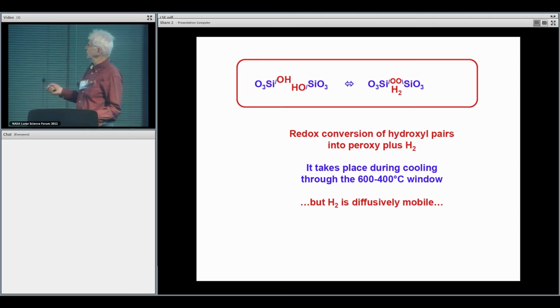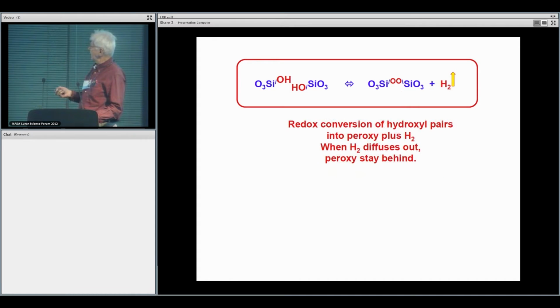This peroxy bond is a very short bond. It's only 1.5 angstrom long. The volume, if you draw a box around it, is barely that of one oxygen. Now, the next slide shows that hydrogen is diffusively mobile and could leave the place where this reaction has taken place, particularly if it has lots of time and additional activation. And if this happens, you would reach a situation which is quite interesting, that the former water content is maintained in the solid in a kind of memory, in these peroxy defects. And therefore, these peroxy defects now represent a memory of the water that was once incorporated in this mineral structure.